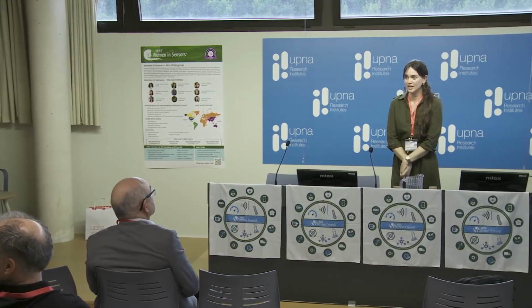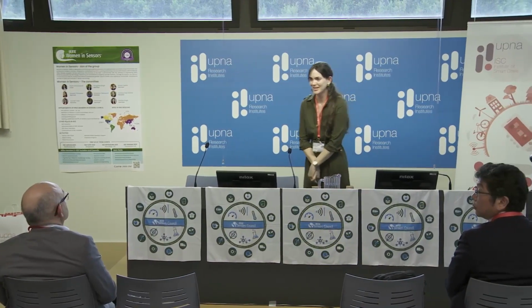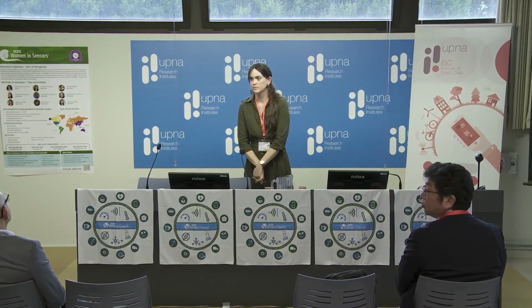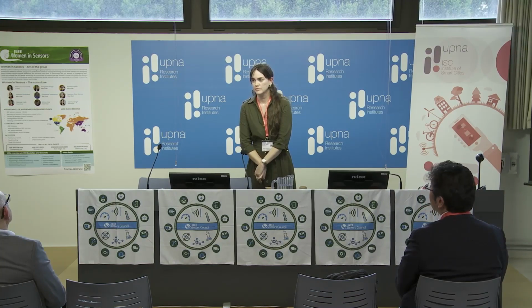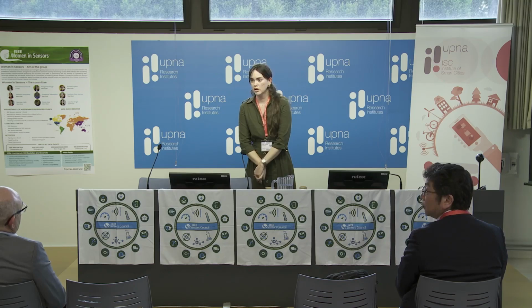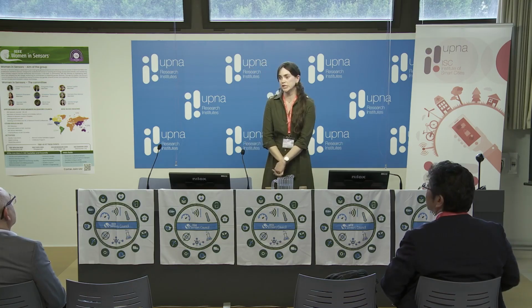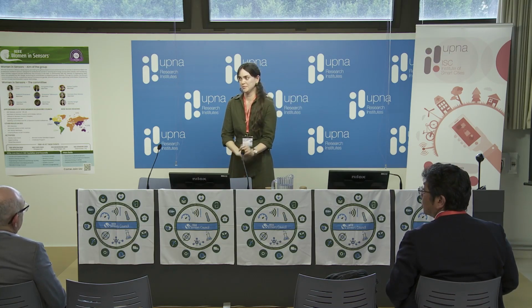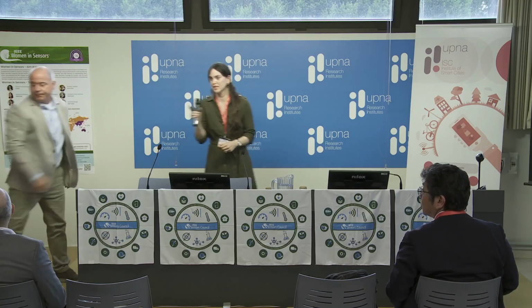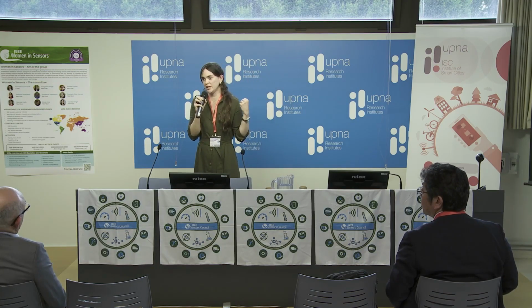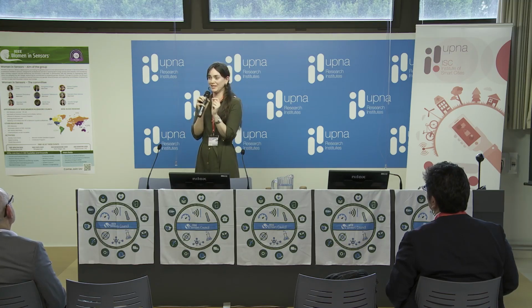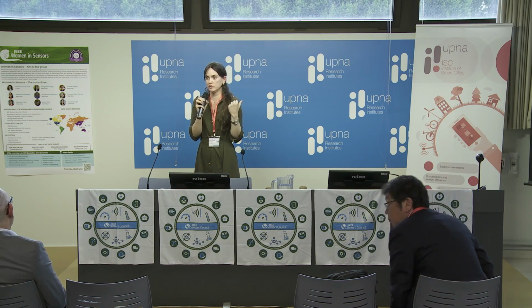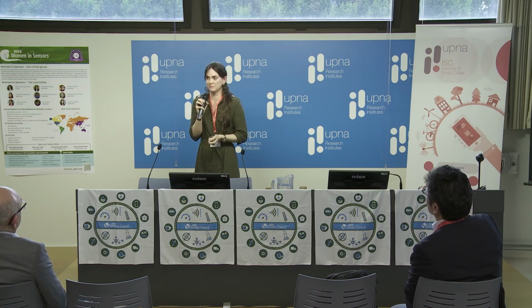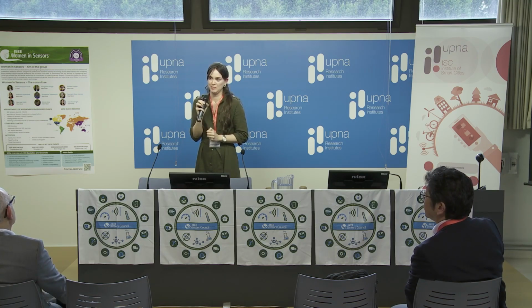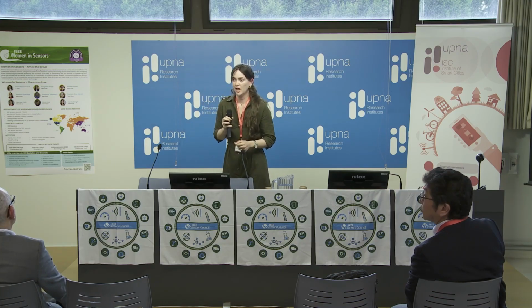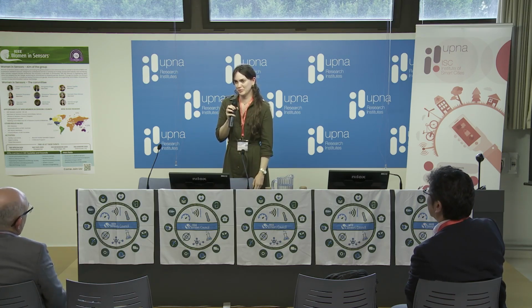I try to ask in English. My English is not so good, but do you find problems during the process, to recover the device? Some like broke the fiber, some like this, or no? No, not in this case, because these optical fibers are of 1 micrometer, so it's very easy to manipulate. When we do the taper, yes, because the reproducibility is one problem, but yes, but with optical fibers with the low.